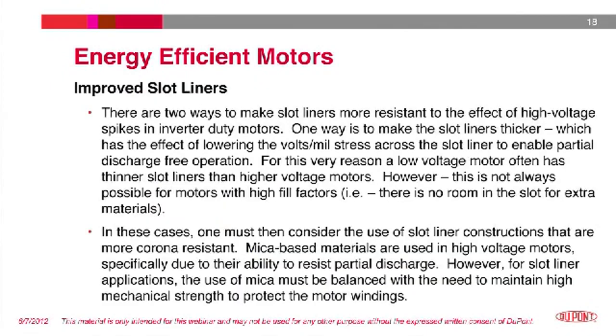motors. There are two ways to make slot liners more resistant to the effect of the high voltage spikes in inverter duty motors. One way is to make the slot liners thicker, which has the effect of lowering the volts per mil stress across the slot liner to enable partial discharge-free operation. For this very reason, a low voltage motor often has thinner slot liners than higher voltage motors. However, this is not always possible for motors with high fill factors. For example, there's no room in the slot for the extra materials.